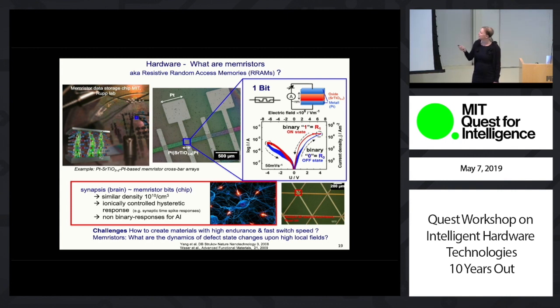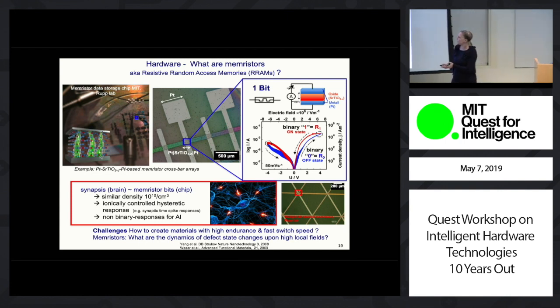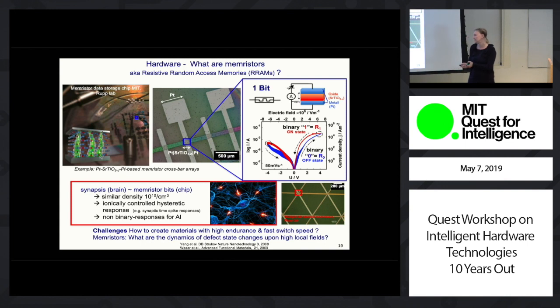So he postulated that there should be such a hysteretic memristive curve, but it took 30 or 40 years until IBM and Hewlett-Packard found that when you go small enough in transition metal oxides, you can find these memristive processes. Now what's quite fascinating is that you can reach a density of these memristors on a chip comparable to 10 to the 10 per square centimeter, which is what we have as synapses in the brain.